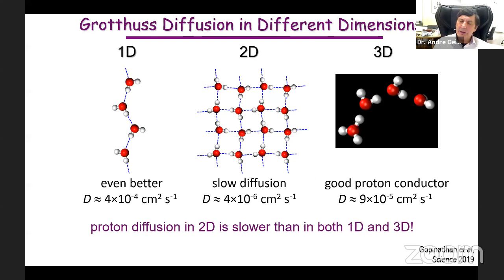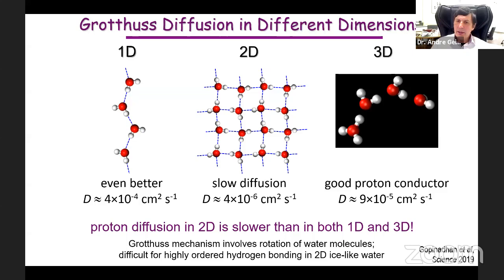If you take nanotubes, where this research has been done as well, mostly theoretically but also a bit of experiment, the diffusion in 1D is even faster than in 3D. So it's unusual: very fast, very slow, fast diffusion. So it's a non-monotonic dependence as a function of dimensionality. There is a minimum in the function of dimensionality. We believe this is happening because water in those channels becomes like ice, very coordinated. Whether it's real ice or another state of matter, we don't know.